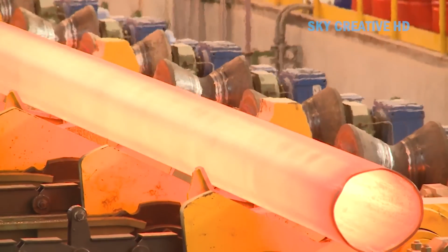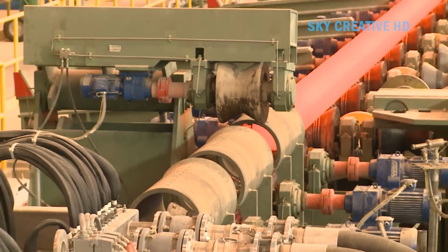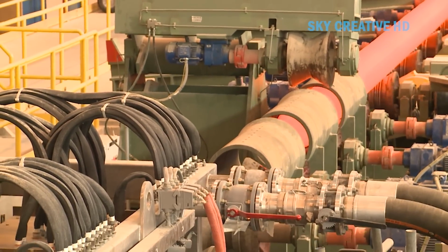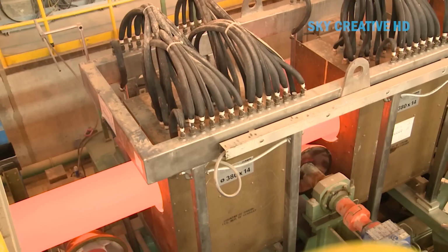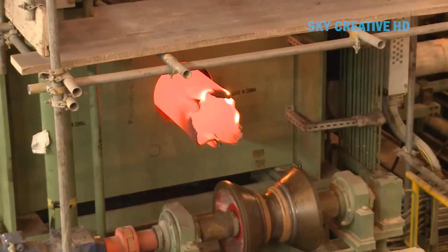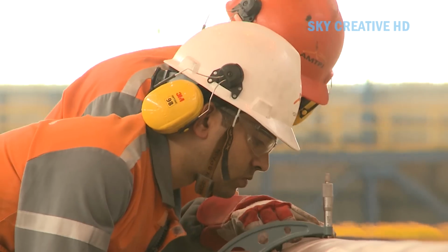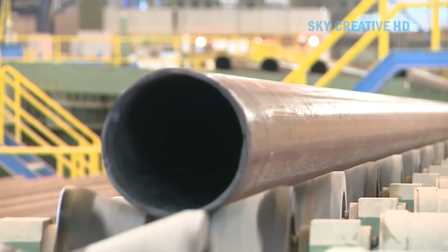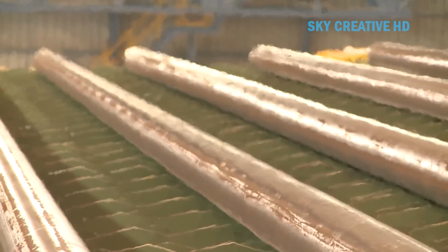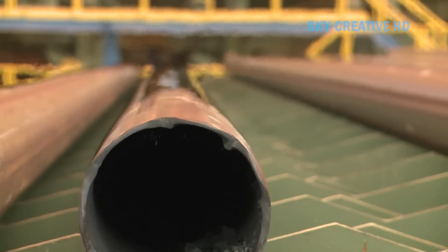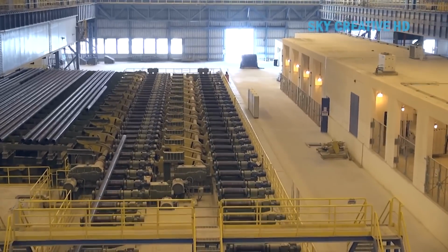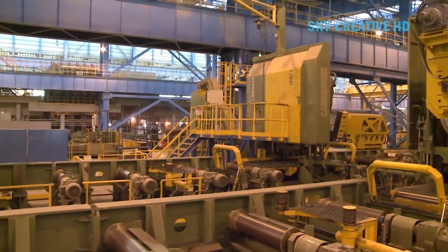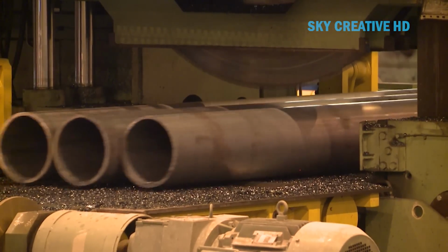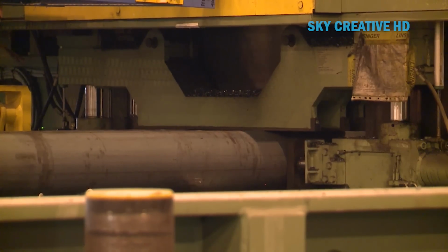Following piercing, the hollow shell undergoes elongation and wall thickness reduction in a plug mill. This mill uses a series of grooved rolls and a plug mandrel to stretch the shell and reduce its wall thickness. The plug mill's precise control over rolling parameters is essential for achieving the final pipe dimensions and mechanical properties. The elongated shell is then reheated and further processed in a stretch-reducing mill. This mill refines the pipe's diameter and wall thickness, providing the final dimensions with exceptional accuracy. The stretch-reducing mill uses a series of closely spaced stands, each with precisely calibrated rolls, to achieve the desired dimensions.